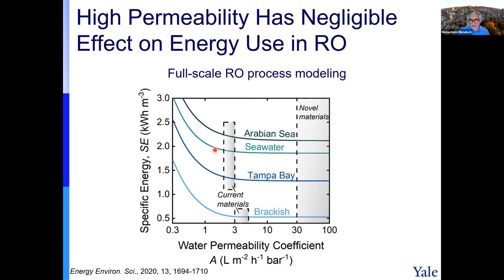And as you see, once you pass a certain water permeability, the energy consumption doesn't drop, because in this case what controls the energy consumption is the osmotic pressure of the exit brine, rather than the membrane resistance. So even if you have a membrane with zero resistance, you still need a lot of energy because of the osmotic pressure of the brine. I started from 0.3, but those of you who know the history of reverse osmosis know the first membrane was cellulose acetate. For cellulose acetate, the permeability was less than 0.3, all the way here. This is why the energy consumption for cellulose acetate was high, and why, with the thin film composite polyamide membrane, we reached almost the optimal energy consumption.